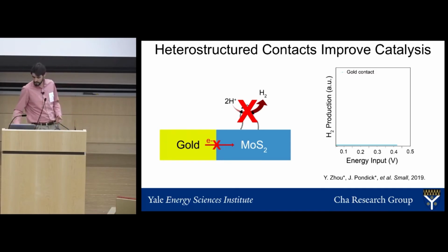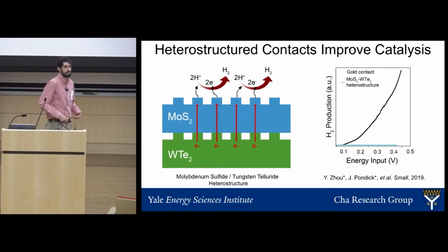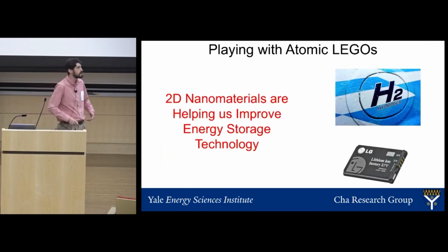So one thing that we did was we swapped the gold contact for a 2-dimensional contact. So we made a heterostructure between tungsten ditelluride, which is another 2-dimensional material, and molybdenum disulfide. And this heterostructured contact does not have a wall for electrons at the interface, which means that now all of the energy we push into the system goes towards making hydrogen gas. And as a result, you can see for the same amount of applied energy, we get a huge increase in the hydrogen that we get out of the catalyst by using the heterostructured contact. So that's just one example of how we use heterostructures in our lab to improve energy storage technology, either by making renewable fuels.